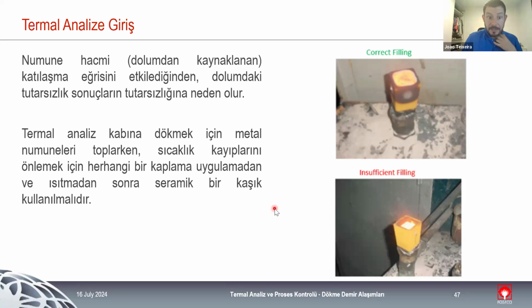But every time that I had some similar problem, I try to calculate the volume of the cup. And we know, for example, that we are adding 4 grams per second for 20 kilograms. And I do a quick calculus to know that for the volume, it is an equivalent amount of inoculant. I add it manually to the cup, and I pour it after treatment on top of the inoculant. And it is not 100% accurate, but it's the most accurate that we can have with this problem.